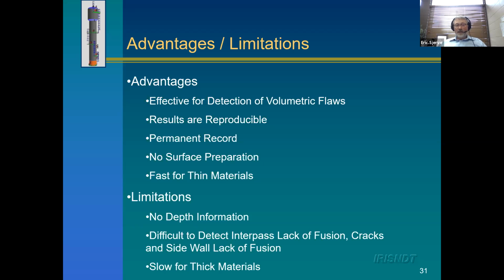With ultrasonic inspection, it's good on thick materials but struggles on thin materials. Radiography is the other way around. It struggles on thick materials because you have to have long exposures, but it's super fast on thin materials. With ultrasonics, you get depth information. With radiography, you don't. So it's almost exactly the opposite of what ultrasonic inspection would be, which makes them a really good fit. Applications that are really good for ultrasonics may not be good at all for radiography and vice versa.